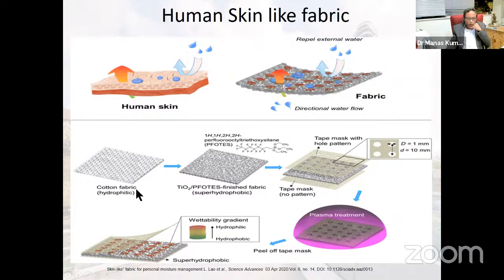So for making this kind of fabric, we took a cotton fabric first, which is hydrophilic in nature. Then it was coated with a super hydrophobic finish. And after that, we heat set it at around 130 degrees centigrade. Then we put a mask. The top mask has small holes. Each hole has a 1 mm diameter, and the gap between the holes is around 10 mm.